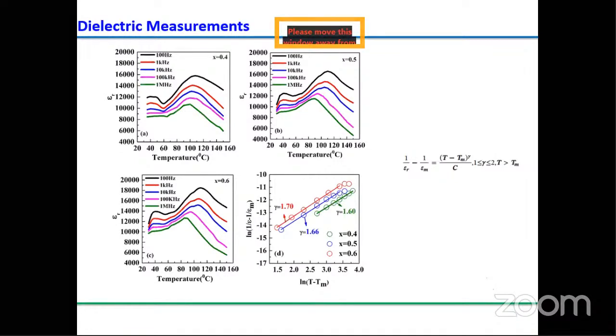Okay. If gamma is equal to 1, it is a pure conventional ferroelectric. If the gamma value is equal to 2, it is an ideal relaxor. We got gamma values of 1.7, highest at x is equal to 0.6, which is closer to the relaxor nature. Ideal relaxor is 2. We got 1.7. So from here, what we can understand is that by changing the composition in BaTiO3, we can induce the relaxor nature in the materials. That is the evidence we got in dielectric measurements.